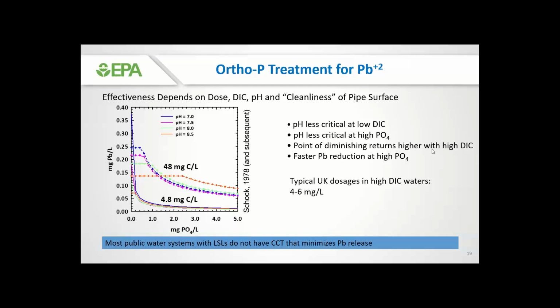And you can see two groups of curves. The top ones have to do with high DIC, dissolved inorganic carbon, of 48 milligrams per liter, whereas the bottom curves represent a low DIC condition of 4.8 milligrams of carbon per liter. If we focus on these lower curves first, the pH is not as important. For these, the curves are pretty close together, and the pH doesn't make as much of a difference as it does for the higher DIC condition. And for the higher DIC condition, the point of diminishing returns for orthophosphate is actually higher. That means we need to add more ortho in the water to start minimizing lead leaching based on this diagram.